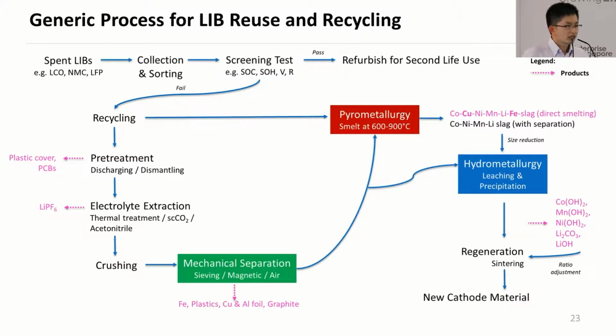Following that, the separated cathode materials can be further size reduced again, and they are subjected to a hydrometallurgy process. This is solution chemistry by means of leaching and precipitation with strong acids to recover the valuable metals, metal complexes. So this includes cobalt, manganese, and nickel. And the ratios of the materials within the leaching solution itself can be adjusted by adding necessary chemicals to replenish and regenerate by means of sintering to produce a new cathode electrode material itself.